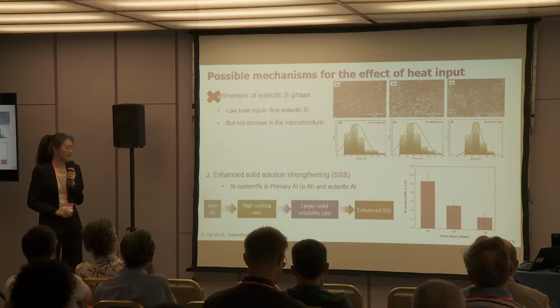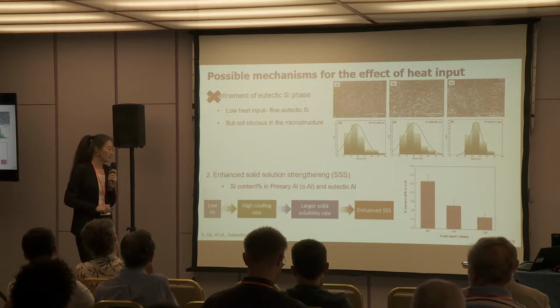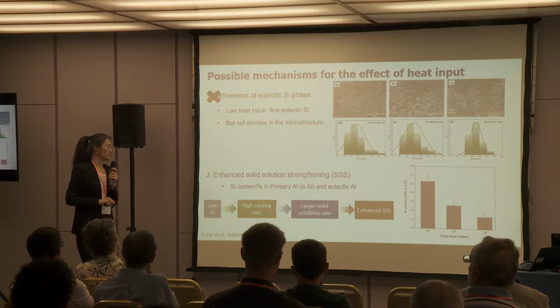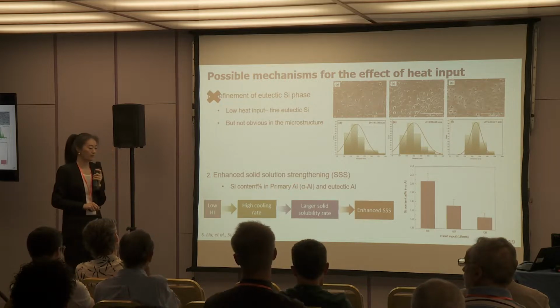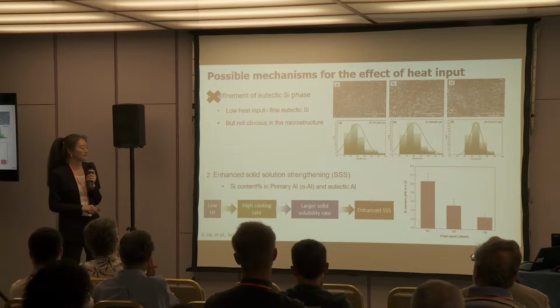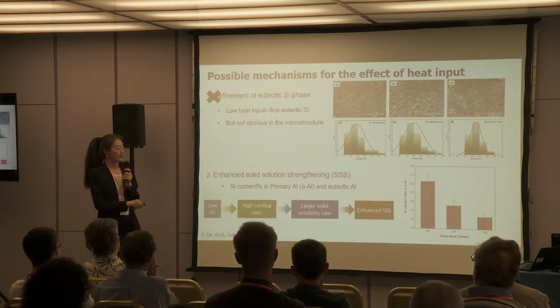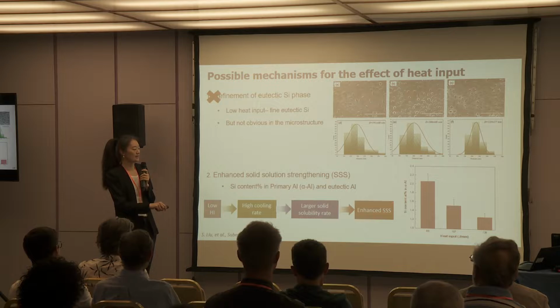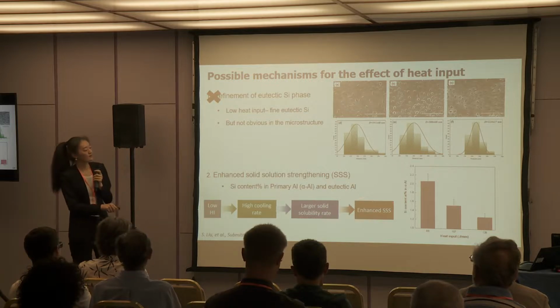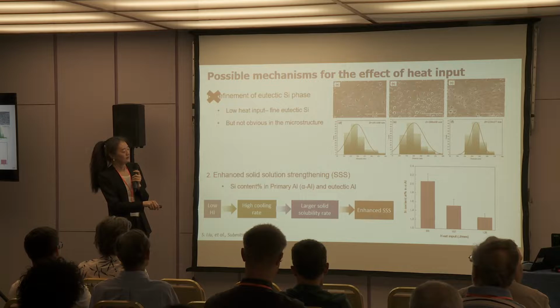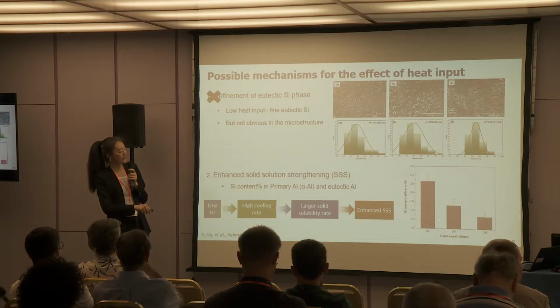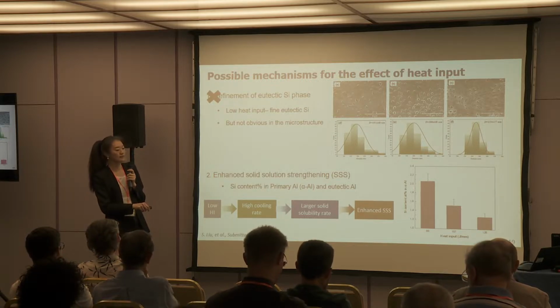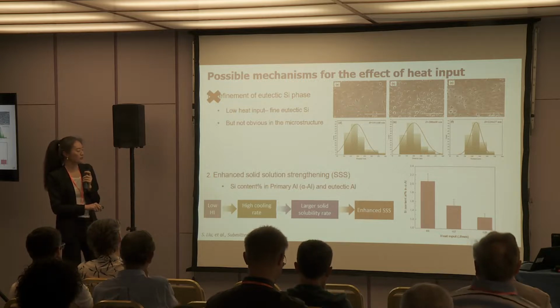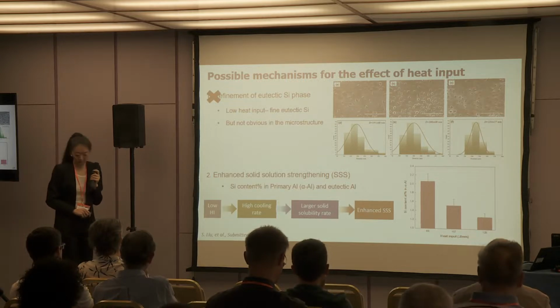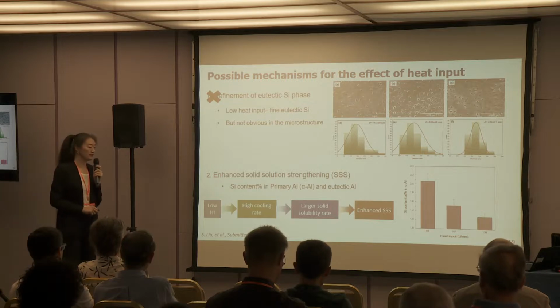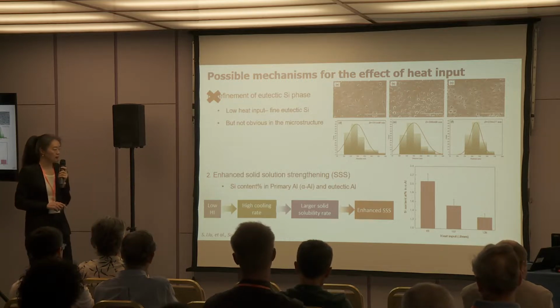And another is that with lowering the heat input, we will be able to strengthen the solid solution strengthening effect. And this is related to the silicon content in the primary phase. From our chemical composition analysis, we confirm this tendency: with lowering the heat input, we have higher silicon content in the primary aluminum. And this contributes to the enhanced solid solution strengthening, and is responsible for the nano-hardness tendency in our research.